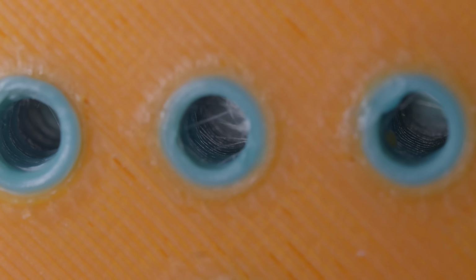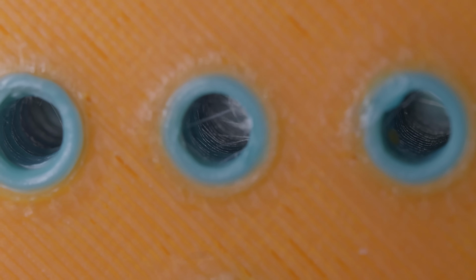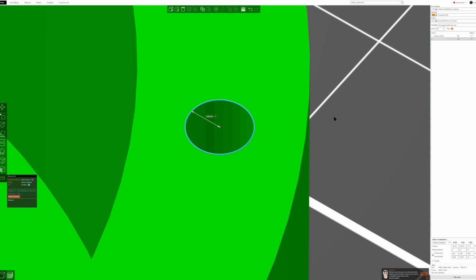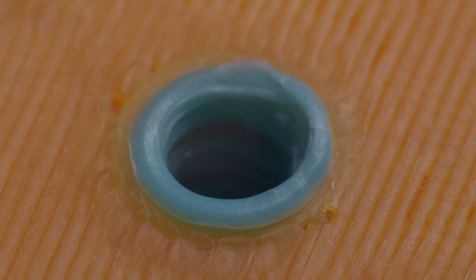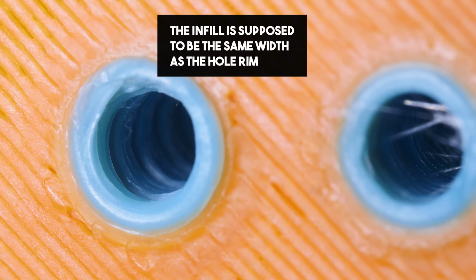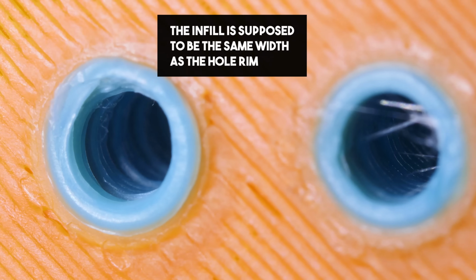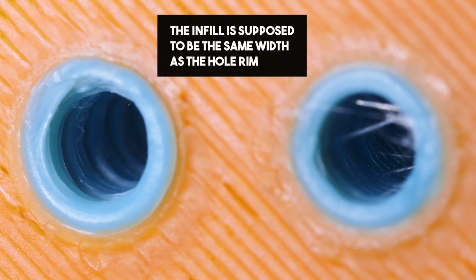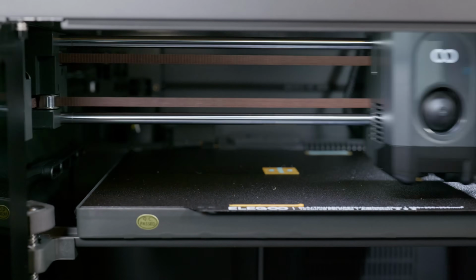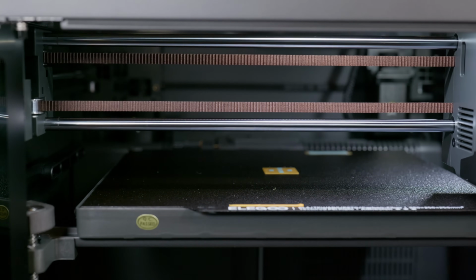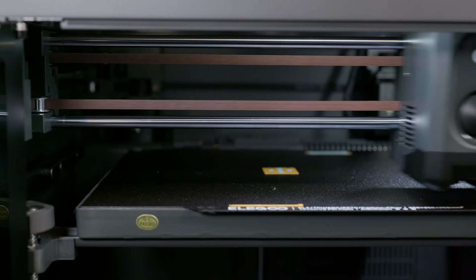But back to hole size, and it gets a bit muddy when we're 3D printing because there's a very good, almost 100% chance that your hole will not be the size that you think it is. The problem is that no matter what order you print the walls of a part in, whether you do outer wall first, outer wall second, the inner hole of a screw hole is always unconstrained, so there is always a tendency to some extent for the material to spill into the void or just not create an accurate hole for a lot of reasons.